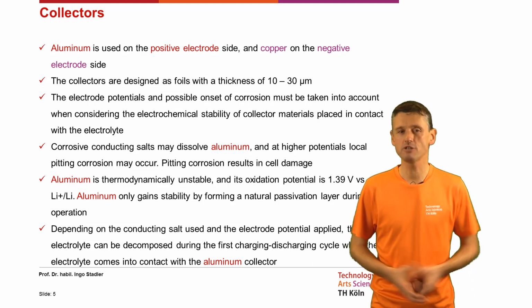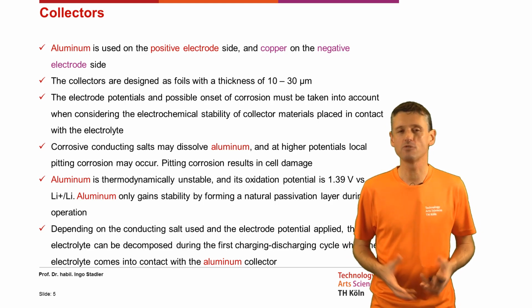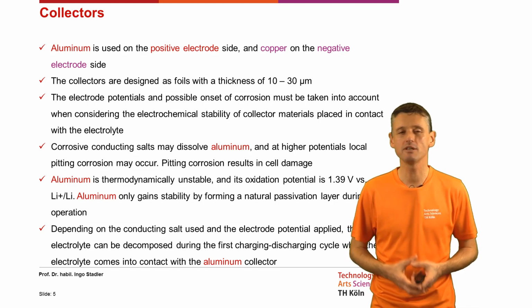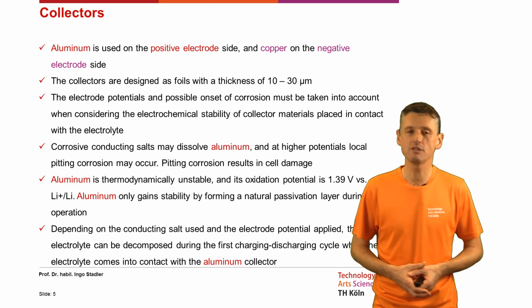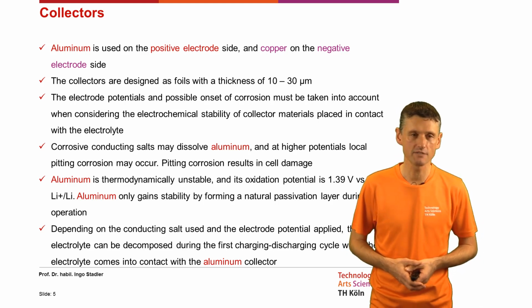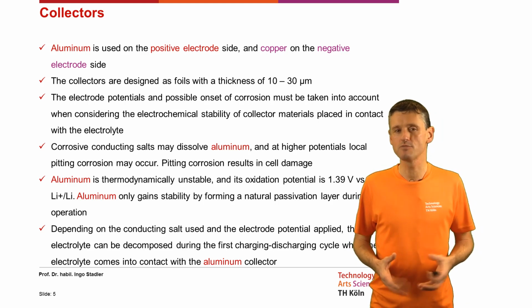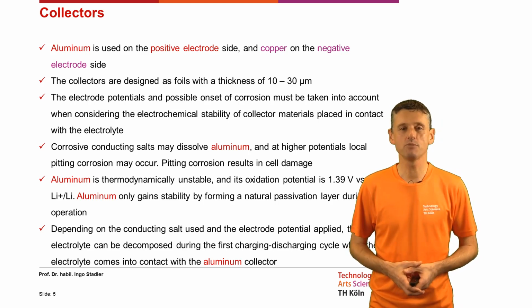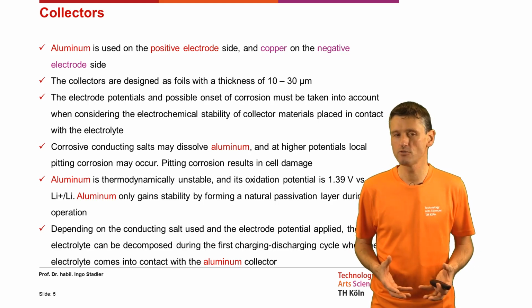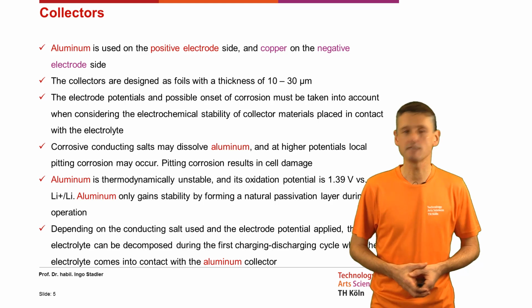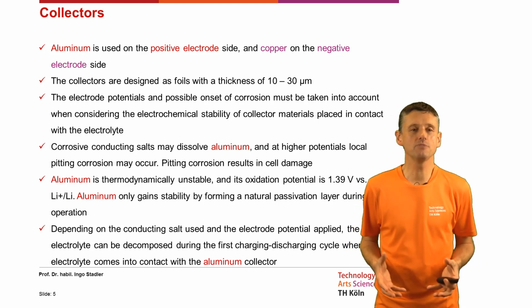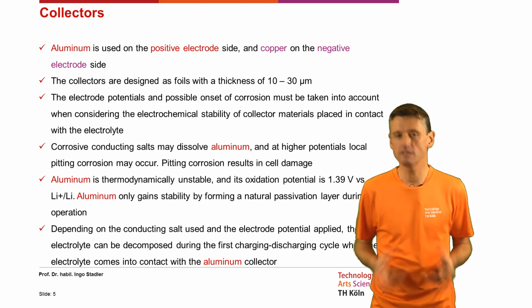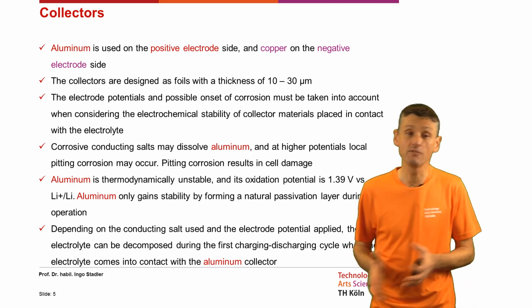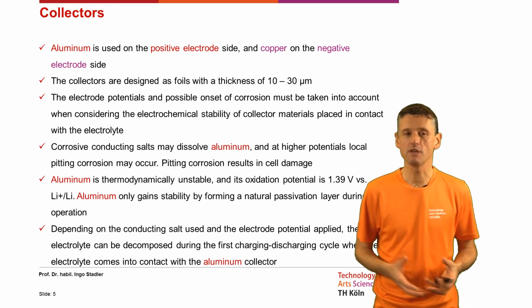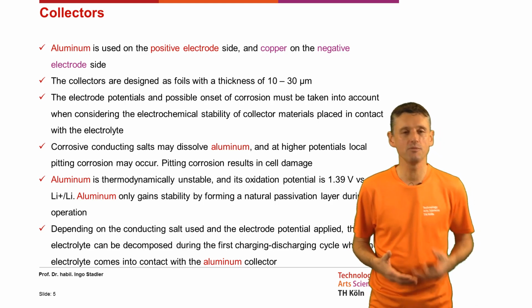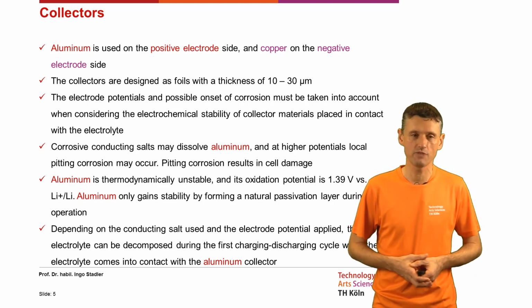The electrode potentials and possible onset of corrosion must be taken into account when considering the electrochemical stability of collector materials placed in contact with the electrolyte. Corrosive conducting salts may dissolve aluminium, and at higher potentials local pitting corrosion may occur. Pitting corrosion results in cell damage. Aluminium is thermodynamically unstable and its oxidation potential is 1.39 volt versus lithium. So aluminium only gains stability by forming a natural passivation layer during cell operation.